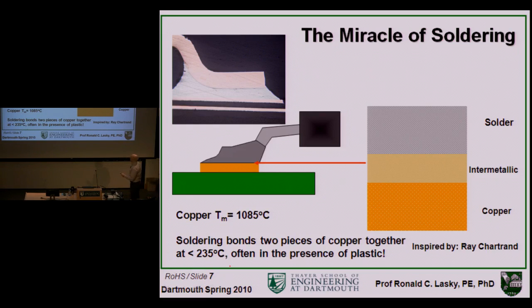This is a schematic of what would be an electronic package. Cut away here, there would be an integrated circuit back up here. Here's a lead that looks gray because it's usually tinned with some sort of material that wets much more rapidly to solder than copper does, but there'd be copper inside. And here's a copper land on a printed wiring board. And here's actually a picture of a real one. Here's the copper land, this thin piece right here on the circuit board. Here's the solder joint, and here's the lead coming off of the electronic package.